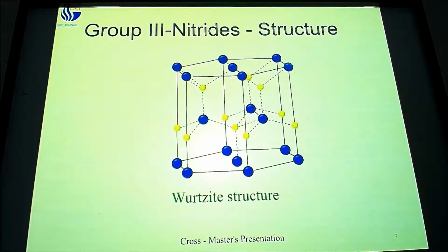We have aluminum, gallium, or indium up here in blue or purple, and then we have the yellows here as the nitrogens. It's a shifted hexagonal lattice structure. So we have 2 hexagonal patterns, one shifted over from the other, and they lay like this with layers A, B, all the way up.